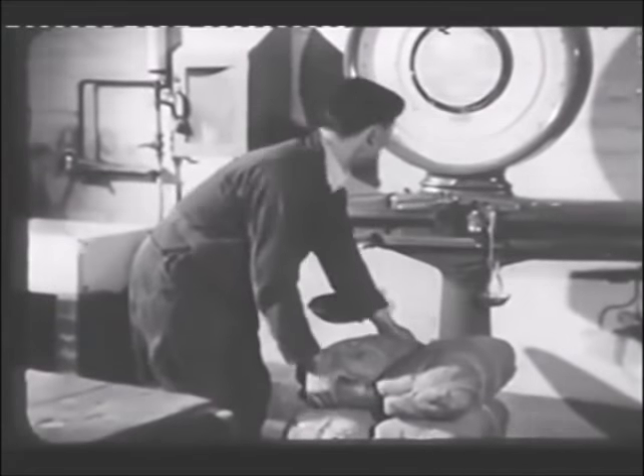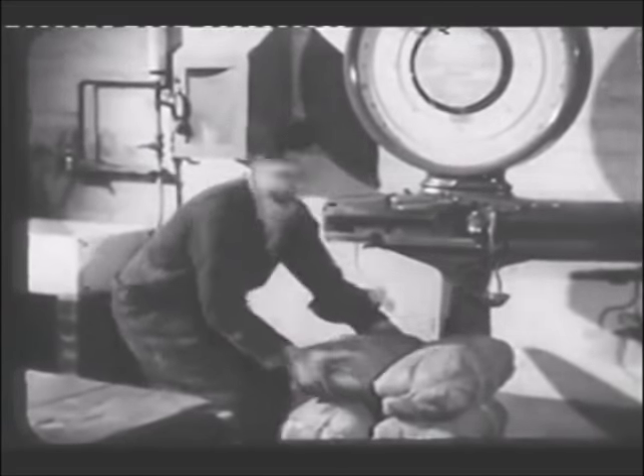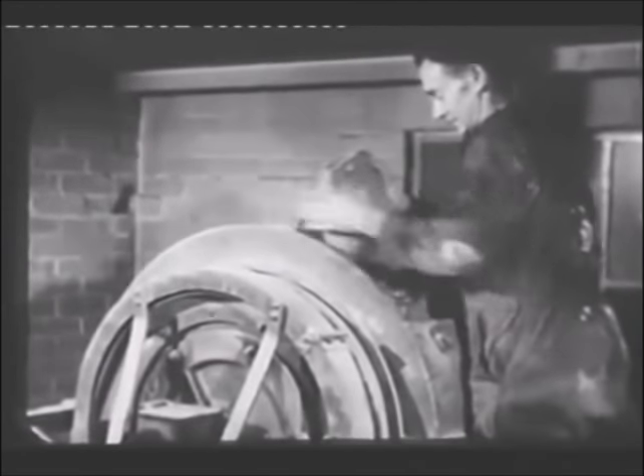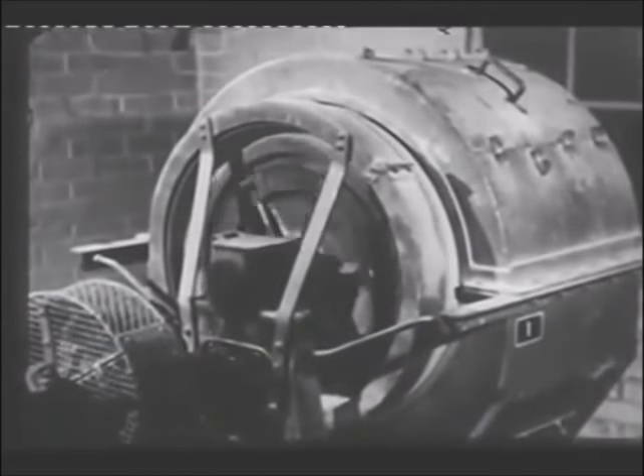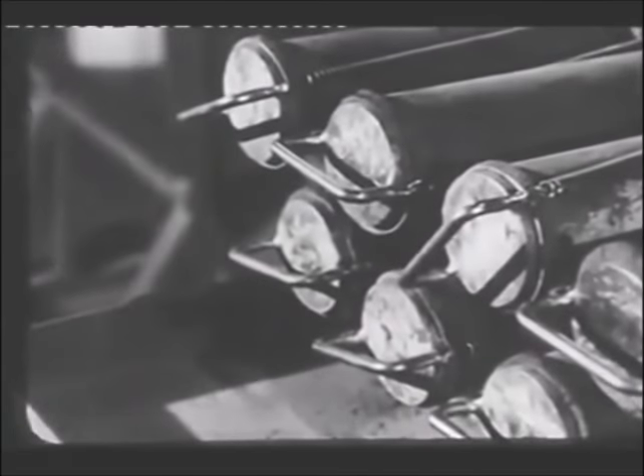The heater is made from tungsten, and tungsten is the metal obtained from scheelite. The scheelite is weighed and tipped into a ball mill. Here it is ground continuously for 7 days to reduce it to a fine powder, which then undergoes various chemical treatments which yield pure tungsten in powder form.